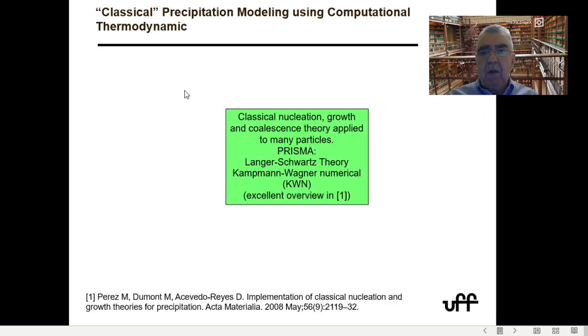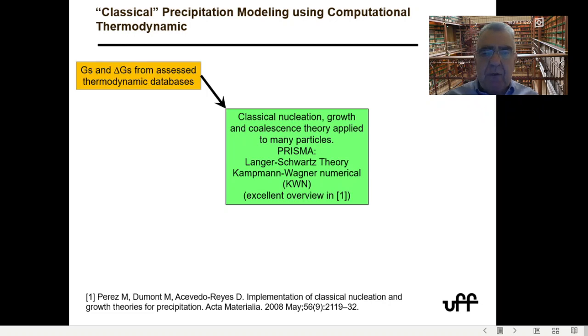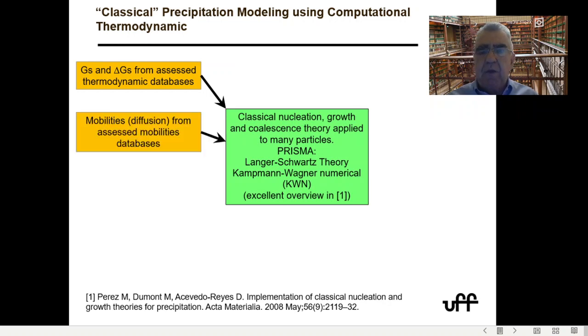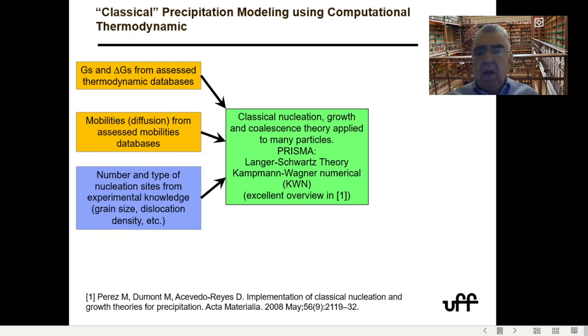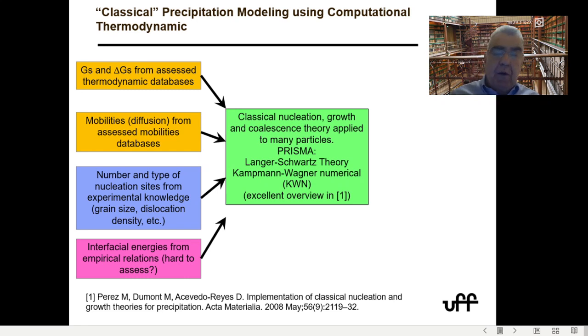Now, when you use classical theory for nucleation and growth, there are some very interesting models now. There are 3 or 4 software packages that do that. You take the thermodynamics, you take the diffusion data, and you take a number of experimental inputs like grain size, dislocation density, and so on. And then if you are able, you also need to know the interfacial energy.